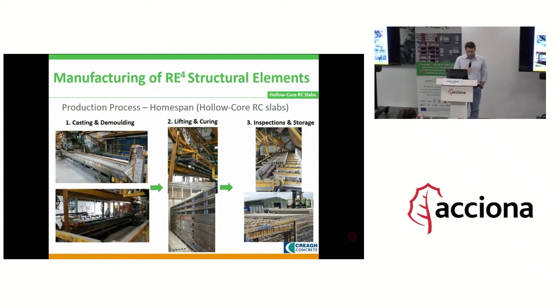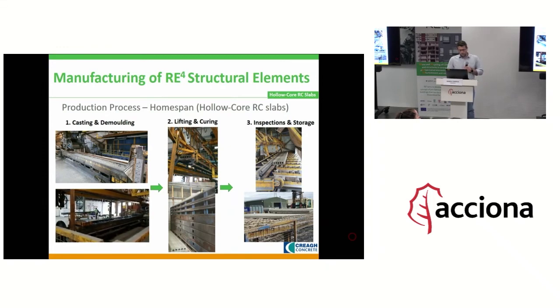I'm not too sure if you can see in the video, but at this point, the pipes that form the hollow cores are being removed, and then the mold is lifted, leaving the slab in that rack. This process is only possible using semi-dry concrete. After this step, the rack is lifted and placed to cure in an adjacent area. Once it achieves the required strength, the slab is pushed from its rack into a conveying system that transports the slabs outside, where the final inspections and storage are carried out.